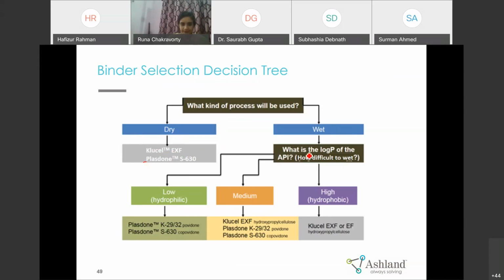Coming to wet granulation, there we need to consider the log P of the API, whether the API is hydrophilic or hydrophobic. If your API is hydrophilic, then we recommend povidone or copovidone. If the API is hydrophobic, then we recommend Klucel EXF or EF, or you can use LXF or LF. If you are mixing the binder with the dry mix, use a finer grade. If you are making a binder solution, use the regular grade, which is EF or LF. If your API has medium hydrophobicity, then you can select any of the binders based on performance.